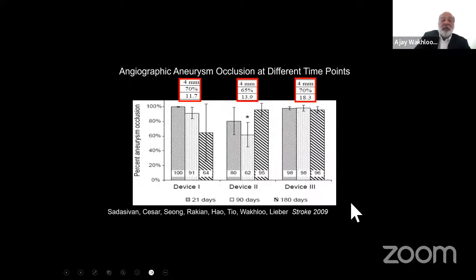And then we added a third one, which had a lower porosity, that means more metal, but had less pores per square millimeter as compared to the other devices. And then we looked at the rabbit occlusion data, and what we found out is that if the samples have the same porosity, in this case 70%, but have twice as many pores per square millimeter, the occlusion rates of these aneurysms was significantly higher and it stayed stable over 6 months.